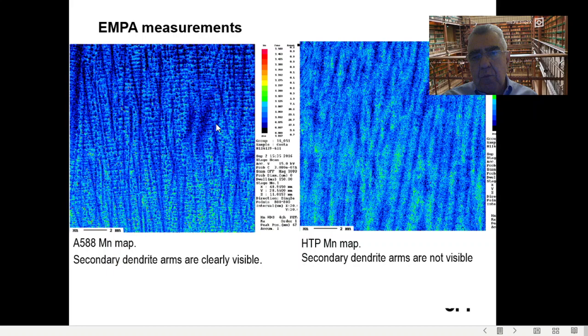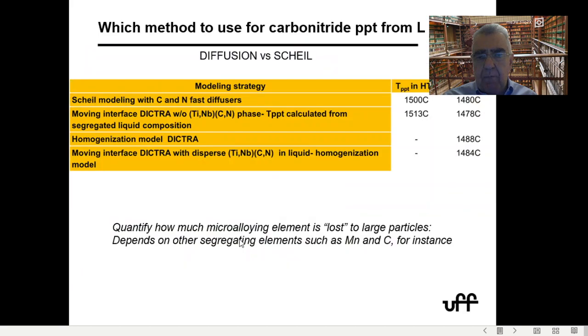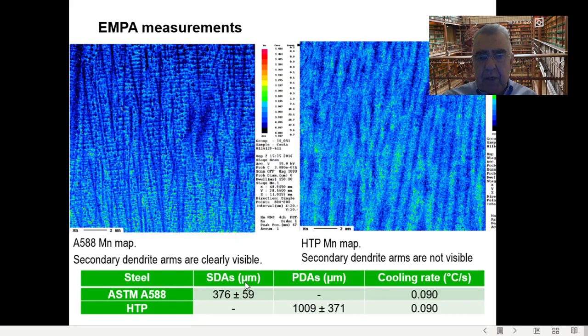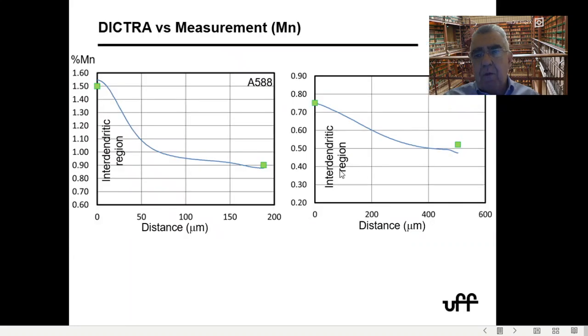So if we do the microprobe for these two steels that I'm taking as an example, we can get the secondary dendrite arm space from this, and for this steel there was only primary dendrite arm space. And then with the Suzuki relationships or any other good relationships, we can derive the cooling rate at this position. Now with DICTRA, we can then model the segregation. If you can see this, the blue line is the segregation as modeled from the center of the dendrite to the interdendritic region, and the green squares are the experimental points from the microprobe.